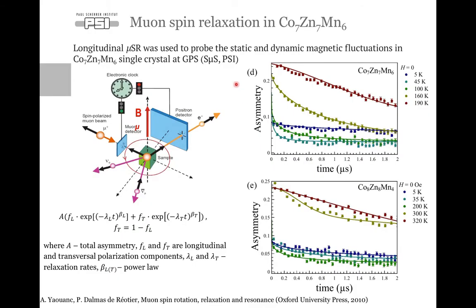Okay, and then let me explain the experimental tools that we used. First of all, the muon spin relaxation, the experiment that we have done at instrument GPS. It's the Swiss muon source at PSI. And we used the muSR in longitudinal geometry that allowed us to probe static and dynamic magnetic fluctuations in cobalt zinc manganese 776 single crystal in the time frame of a few microseconds.